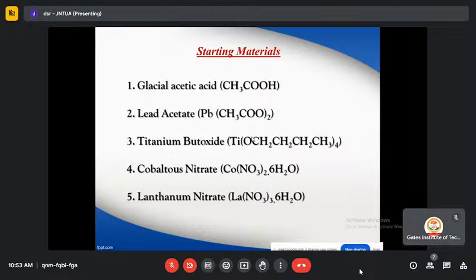Now, in order to prepare these cobalt-based nanomaterials, the materials that we have used are glacial acetic acid, lead acetate, titanium butoxide, cobaltous nitrate, and lanthanum nitrate. So coming to the process of preparing this, initially the samples are processed to make a dispersible oxide which forms a sol, that is a precursor, in contact with dilute acetic acid or water. Removal of the liquid from the sol yields the gel, and the sol to gel transition controls the shape and size of the particle.